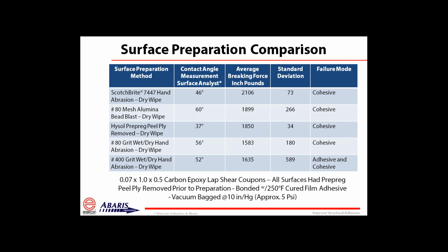So obviously by abrading, we note that we have changed the contact angle measurement some by changing the physical characteristics on that surface, and we've increased the average breaking force. Now, the other thing that you might look at in this is that with other methodologies, you might end up with a fairly high contact angle, and still get a suitable breaking force, but you might end up with a high standard deviation amongst your test specimens. And that means that you're not getting consistency.